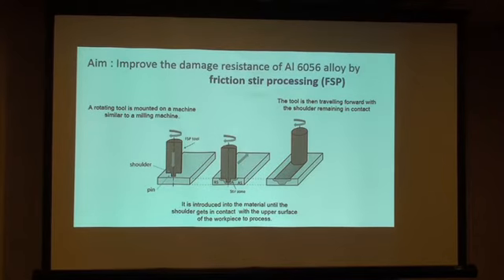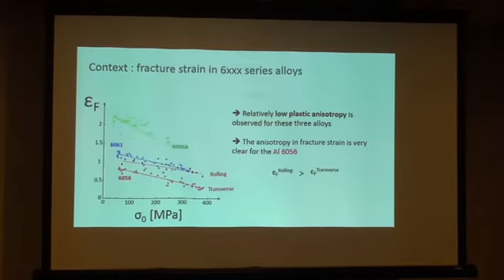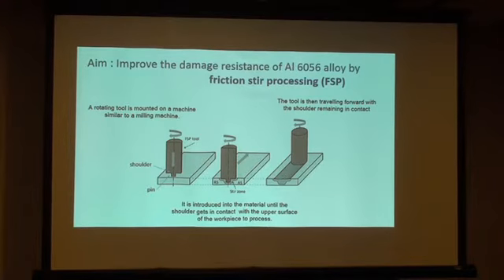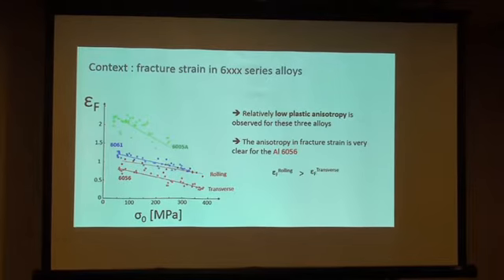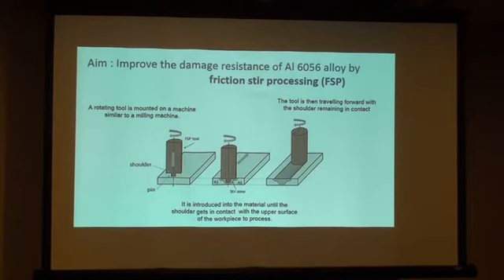So, because of this observation, we came with the idea that we could improve the ductility of the aluminium 6056, so the one with the lowest ductility and which exhibits anisotropy, by applying friction stir processing. For those of you who would not be familiar with this technique, it's almost the same as friction stir welding, except that you do not weld anything, you just process the material. So you've got a rotating tool which is mounted on a machine which is similar to a milling machine.